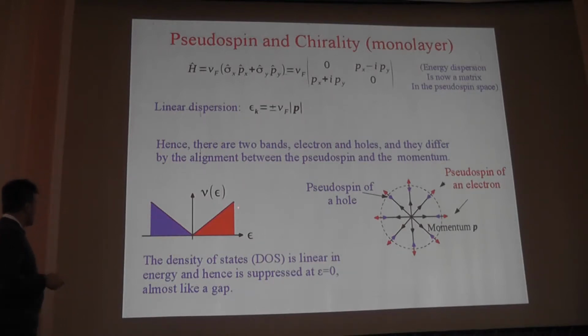That's one important point. Another thing which should be mentioned is that with a spectrum like this, it's often instructive to characterize it by looking at the density of states: how many states are available for a particle at each particular energy. For the linear dispersion, you can apply the standard equations from any statistical mechanics book, and here's what you get. The density of states is suppressed near the charge neutrality point and increases away from this point. Here you have the band of electrons, here you have the band of holes. They touch just at one point, just at one quantum state. So you can smoothly change electrons into holes almost at no energy expense, but there is a very small number of quantum states here, so quantum mechanics becomes interesting.